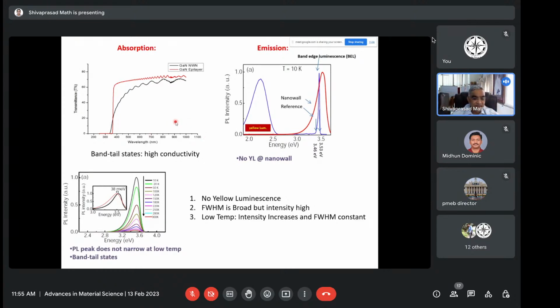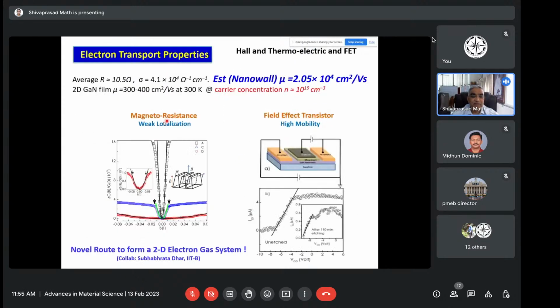Okay, and so I collaborated with Subhabrata Dar from IIT Bombay. He is an expert in low temperature measurements, so we tried to understand what. So we did this in terms of making an FET out of that. Then we looked at the mobility, and the mobility of this material showed very large mobility, almost 20,000. Though for a 2D GaN film, gallium nitride, it should not be more than around 300. But now we are seeing 20,000. So what is the cause for this?